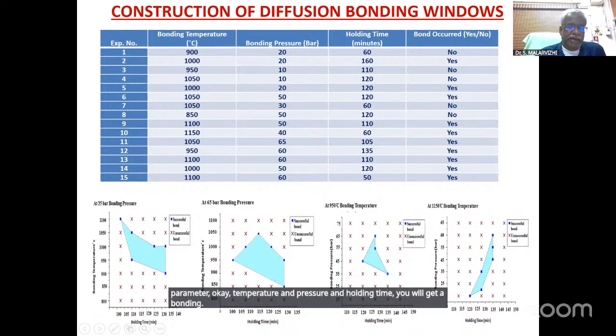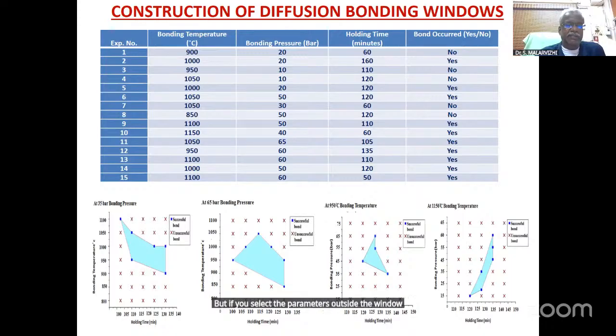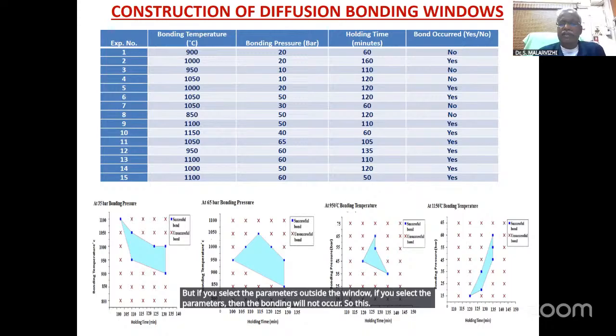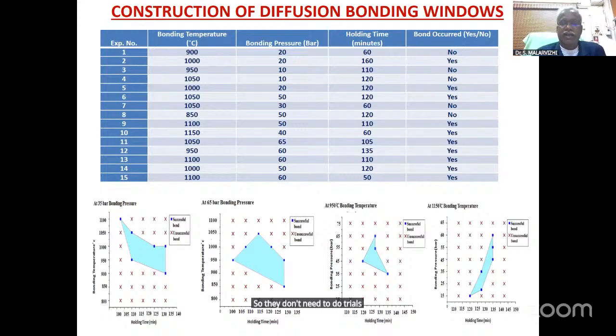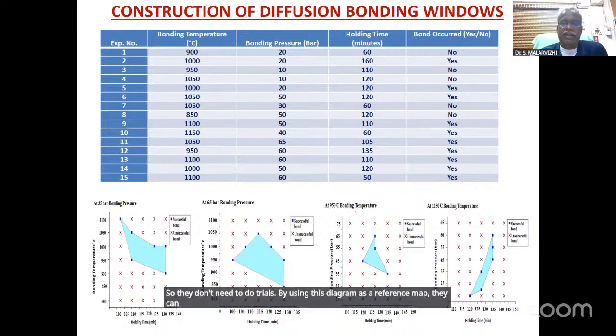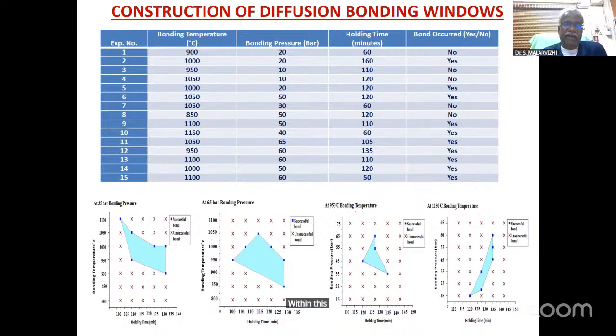But if you select the parameters outside the window, then the bonding will not occur. So this kind of diagram will be helpful to the engineers. They don't need to do trials. By using this diagram as a reference map, they can select the optimum parameter. But within this domain of the processing map, where the maximum strength will happen, that we used again the RSM and we found that.